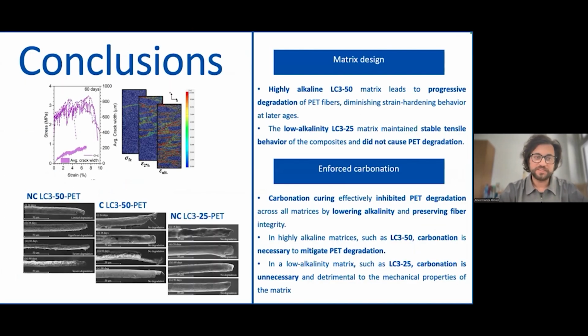And this brings me to the conclusion slide, and I will conclude from two perspectives. One is from the matrix design, where we can say that the highly alkaline LC3-50 matrix leads to progressive degradation of PET fibers, diminishing strain hardening behavior at later ages. However, the low alkalinity LC3-25 matrix maintains stable tensile behavior of the composites and did not lead to any PET degradation. From the carbonation standpoint, carbonation curing effectively mitigates the PET degradation, lowering the alkalinity and preserving the fibers. It's actually necessary to carbonate the high alkalinity matrices such as LC3-50 if you're using PET fibers to protect them. But in low alkalinity matrices, carbonation should be avoided.